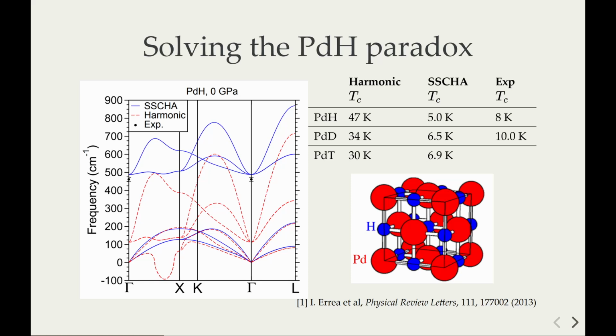Now we can apply this to palladium hydride and look at what it looks like. We immediately see we can compute phonons from the effective phonons inside the theory, which is a bit like computing the band structure from the effective band structure we get from density functional theory. And what we immediately notice is that the agreement with experiment on the phonons is restored, is much better.